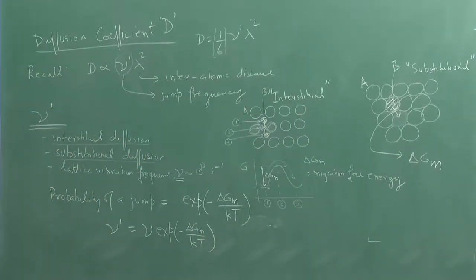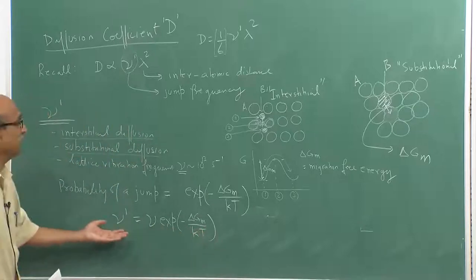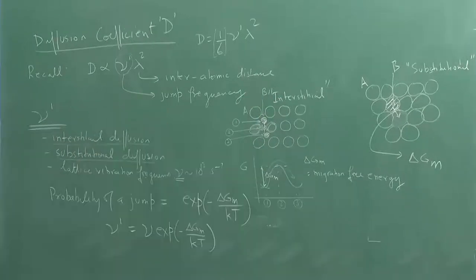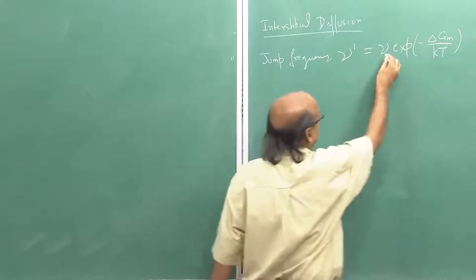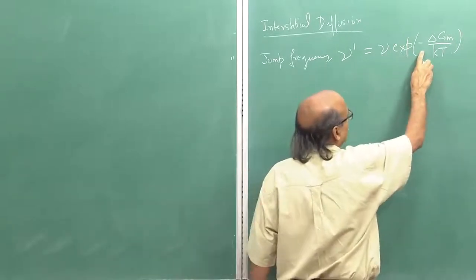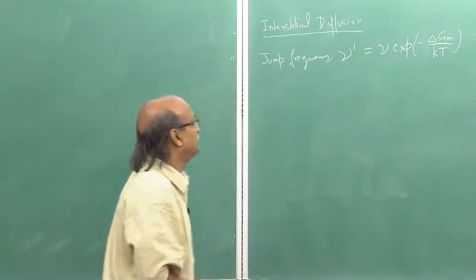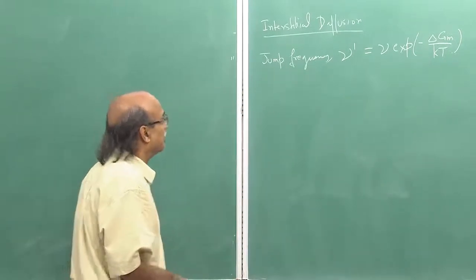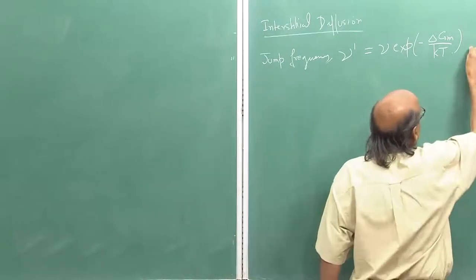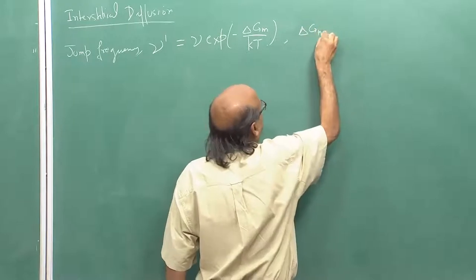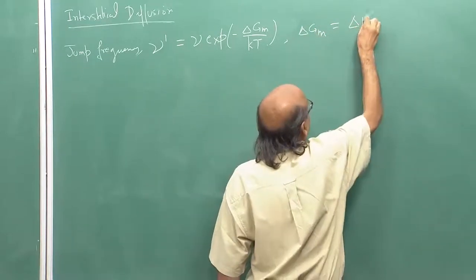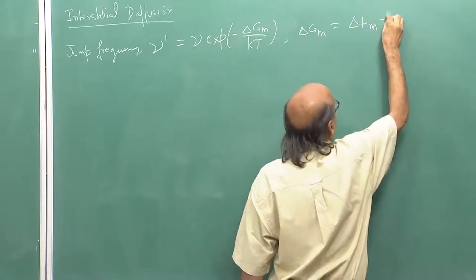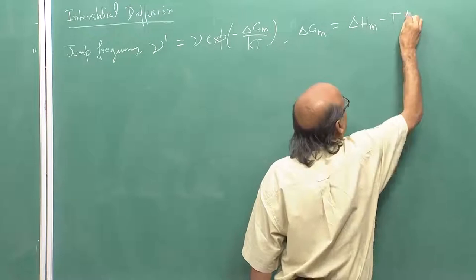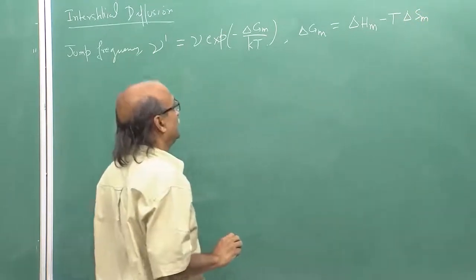Now, this is the situation for the case of interstitial diffusion. So, we have seen that in the case of interstitial diffusion, jump frequency nu prime is given by nu, the lattice vibration frequency, multiplied by exponential minus delta Gm upon kT, where delta Gm is the migration free energy for the jump. Now, we can write delta Gm in terms of enthalpy and entropy as delta Hm, the enthalpy for migration, minus the temperature at which the jump is taking place, times the migration entropy delta Sm.